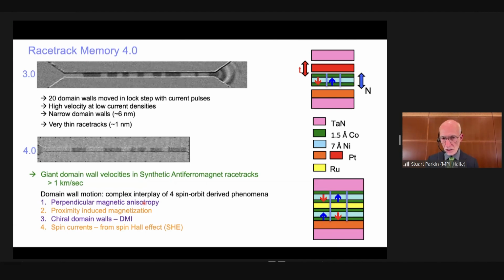This is key to their motion in the same direction under the influence of spin currents derived from the spin Hall effect. On the right-hand side, you can see in a cartoon form the structure of the simplest racetrack. In the top, the racetrack is a simple ferromagnetic racetrack, and the racetrack itself is composed of the green and blue layers. These are formed from cobalt and nickel layers, each one just 1 to a few atomic layers thick, a few angstroms of cobalt, a few angstroms of nickel, a few angstroms of cobalt. This makes the racetrack. It's 1 nanometer thick.